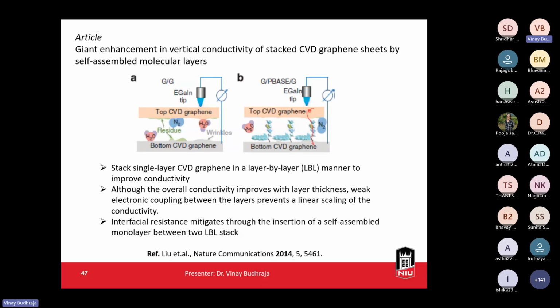Now let's see what different research groups say. And again, I'm just providing one or two examples of each technique. So this article was published in Nature Communications. It's a giant enhancement in vertical conductivity of stacked CVD graphene sheets by self-assembled molecular layers. So they grew the graphene stack from the CVD technique. The advantage of graphene is the high conductivity. So they compare two cases, one the graphene to graphene stack layer, another graphene and self-assembled monolayer and graphene. And they found that with the deposition of the PBASE, the conductivity further improves. And both processes were done from the CVD.